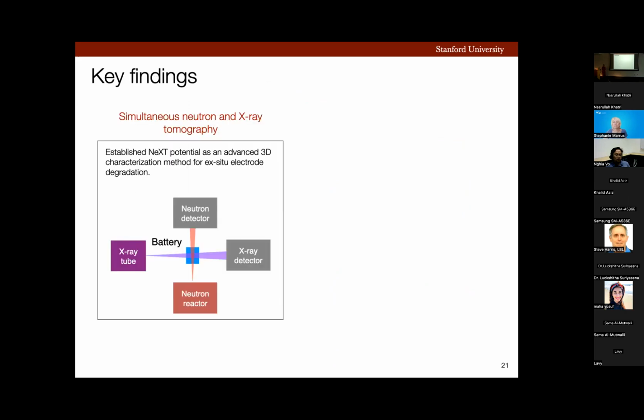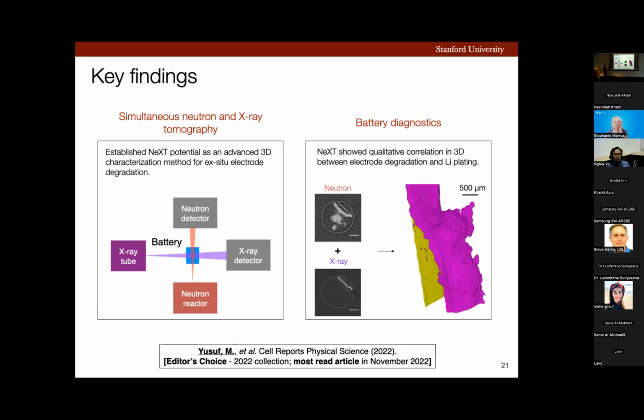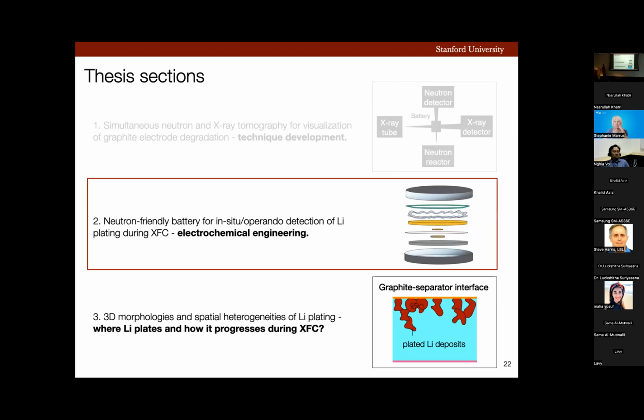Thus, to summarize, in this work, I established the feasibility of simultaneous neutron and X-ray tomography for ex situ 3D battery diagnostics. In addition, this work demonstrated qualitative correlation between electrode degradation and lithium plating. However, you would notice that this work was done ex situ, which means I opened the battery, cut a strip, and then imaged it. To answer the proposed questions, we need to carry out in situ imaging. And this work made me realize that in order to carry out in situ imaging, I need to design a neutron-friendly battery to leverage high-resolution imaging for lithium plating detection, which is what I did in my next project.